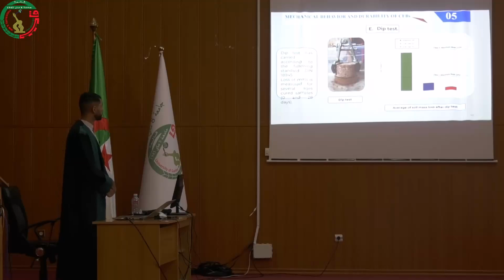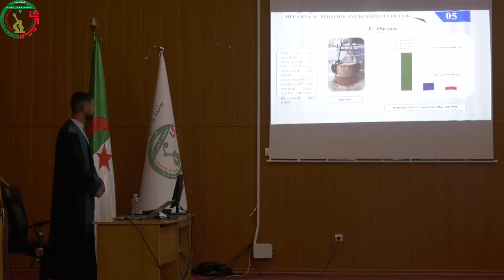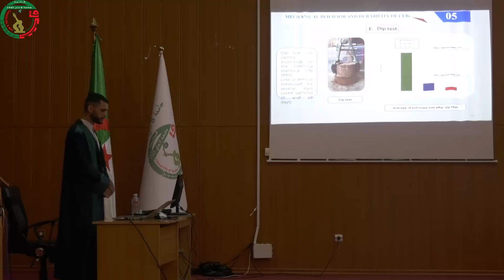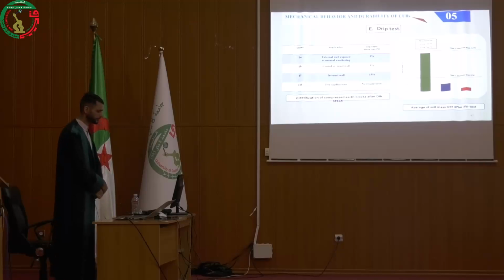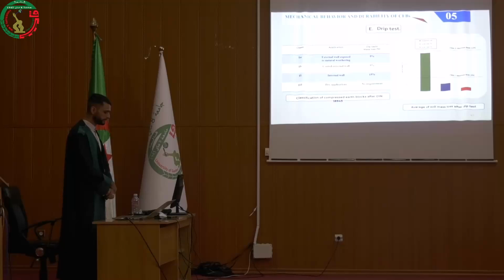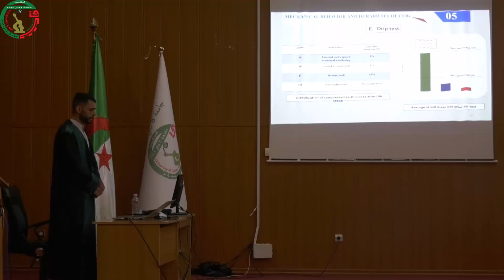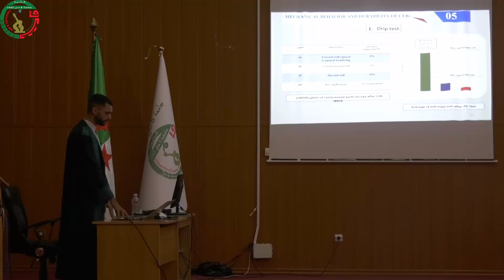We can conclude that the addition of biopolymers significantly improves the erosion resistance of earthen materials. The dip test was carried out according to the following standard. Loss of mass is measured for several ages of cured samples, 0 and 28 days. The untreated samples gave a soil mass loss of nearly 13% and can be classified in class 2, while the 1% and 2% carob gum treated samples gave 2% and 1.5% soil mass loss respectively and can be classified in class 1. According to the classification, the untreated sample can be used only in internal walls, while carob gum treated samples can be used in external walls exposed to natural weathering and coated external walls.